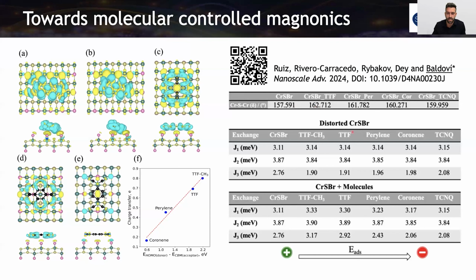If we take just the distortion, we remove the molecule from the calculation, but we have the distortion that each molecule is doing on the chromium sulfur bromide. We observe here in J3 this decreasing. But when we add the molecule in the calculation, we activate this charge transfer. And here it is important that this is clearly increasing, especially for the molecules that are more donor, TTF-CH3 and TTF. These are increasing the J3. In all cases they are increasing from the distortion, but in these cases, even from the pristine material. And as we can see, the TCNQ is not doing any effect, it keeps just the distortion. It's the only thing it's doing on the surface of chromium sulfur bromide.